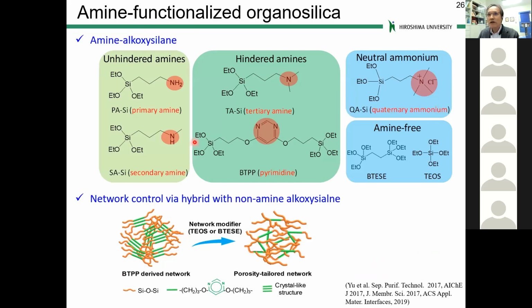Now, we also have worked on amine silica membranes. After a series of experiments, we categorized amine-type alkoxysilane as unhindered amine and hindered amine. Unhindered amine is primary amine and also secondary amine. Hindered amine is like a tertiary amine or pyrimidine type, where the CO2 can directly access this kind of amine functional group. On the other hand, with hindered-type amine, direct contact between amine and CO2 is a little bit difficult. It is hindered.